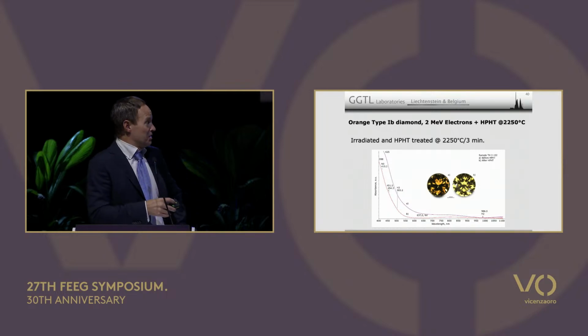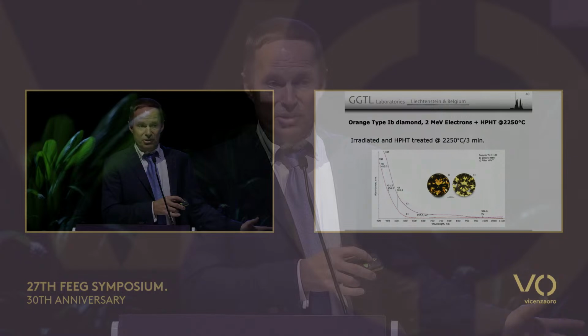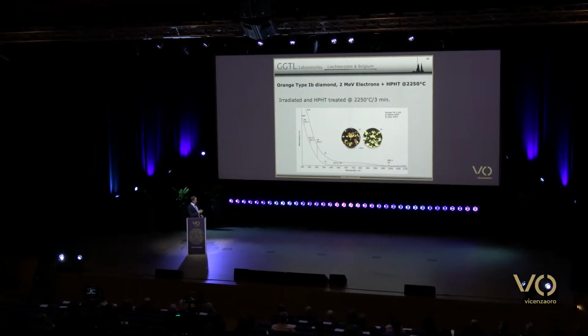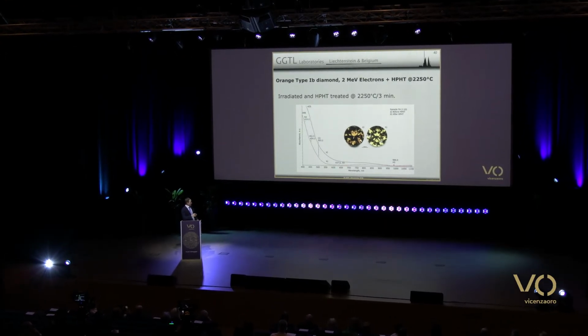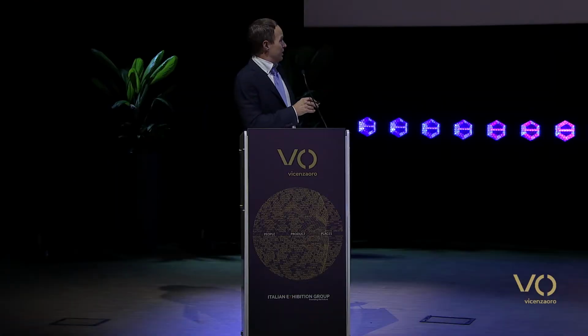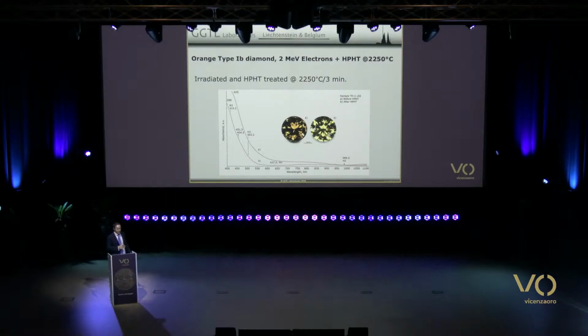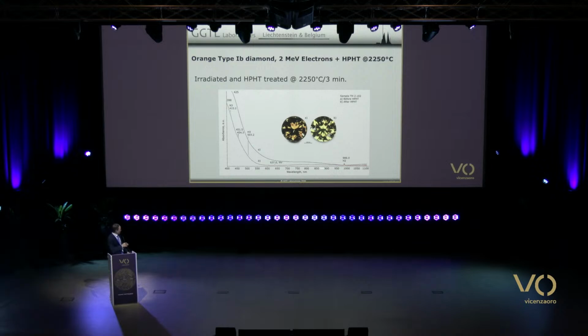Looking at orange, it does the same. You have an orange stone, brownish orange. Why is it brownish orange? Well, people said more nitrogen, or I don't know what. No, it's not. It's plastic deformation. So this stone, a deep brownish, yellowish orange color, before HPHT treatment has this spectrum here. After HPHT treatment, the stone turned bright yellow, and this is the spectrum you have. What's the difference between the two? This continuum here. After treatment, your continuum starts around 560. Before the treatment, your continuum starts already at 950 nanometers.